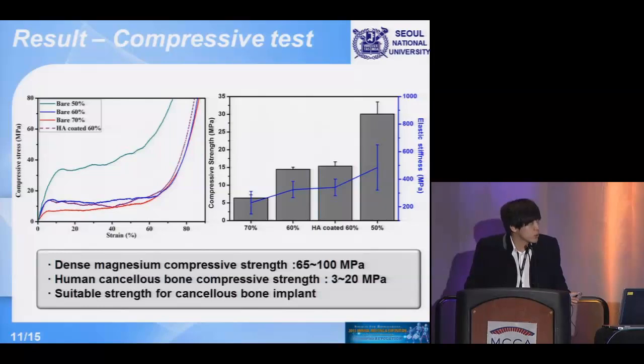because human cancellous bone has a yield compressive strength from 3 to 20 megapascal, we concluded that this porous magnesium has sufficient strength for cancellous bone applications.